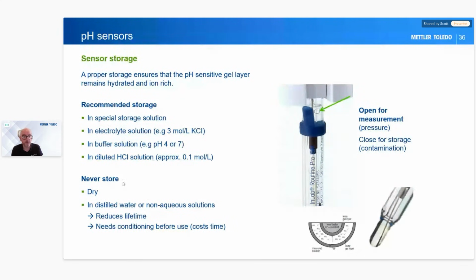So things we never do. We never store the electrode dry. If we store it dry, what happens is that gel layer at the bottom, on the end of the bulb, becomes dried, it shrinks and then pulls away from the glass. If it pulls away from the glass, you don't have the contact to allow the hydronium ions in and out. So we must make sure that we store it as wet or as hydrated all the time, so in some sort of solution.